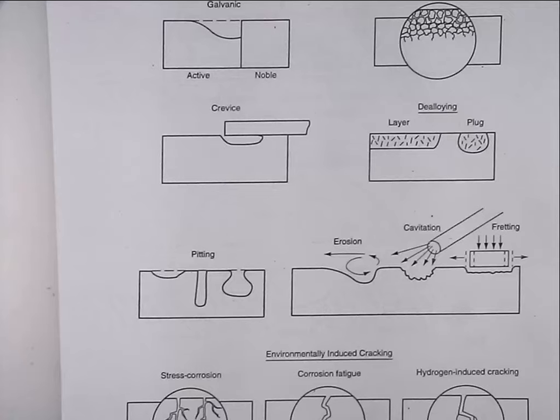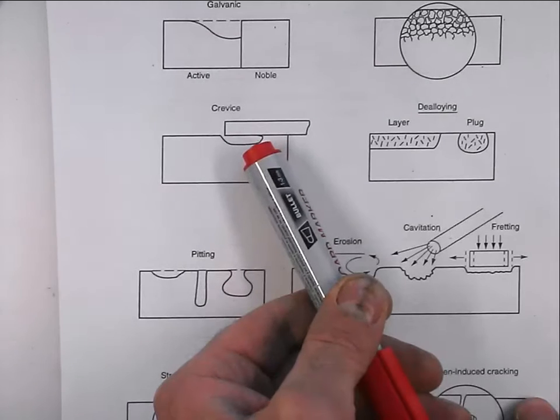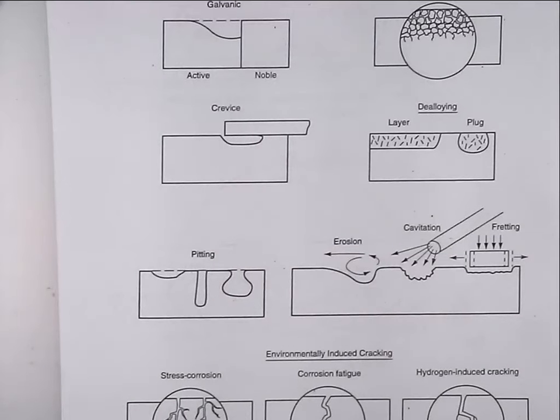And what we found was that these modes of corrosion are strongly influenced by the availability of oxygen for the cathode reaction. So areas that are low in oxygen become anodes, areas that are high in oxygen become cathodes. And after a little bit of initial random anode and cathode production on your steel, they will migrate to areas of high oxygen concentration for the cathodes and low oxygen concentration for the anodes. So inside a crevice, inside a capillary, that's a low oxygen area, and that would be an anode.